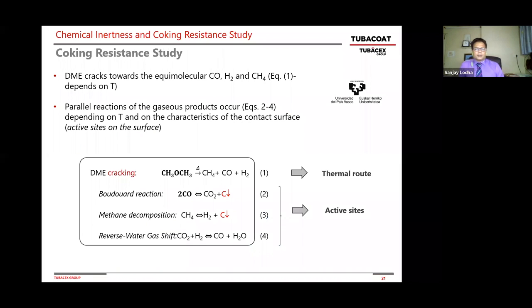So this experiment was done with a European university, where we took the chemical compound dimethyl ether and cracked it. If we crack it properly, it's equimolar cracking into carbon monoxide, hydrogen, and methane, and it won't generate any coke. That's a thermal route. But it doesn't happen in real life. You have many side reactions, the Boudouard reaction that breaks down the carbon monoxide to CO2 and carbon, and methane decomposition, again into hydrogen and carbon. And this carbon is what you don't want in the furnace tubes. Next slide, please.